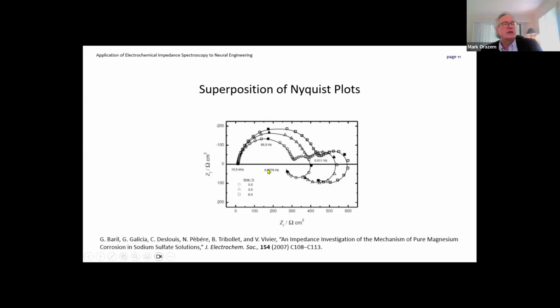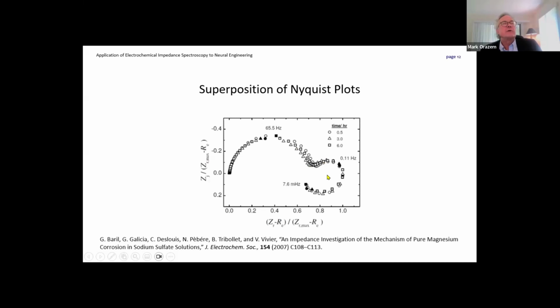The third one I'd like to show is for corrosion of magnesium in a saline solution. And what we're seeing here are 3 measurements taken at different points in time, about 3 hours separating these 3 scans. And what was done here was to choose this point where the impedance crosses the real axis to be the reference point. And what we see is that when we use that, and you can see that the reference point is here because that number is 1, once again, all those points superpose.